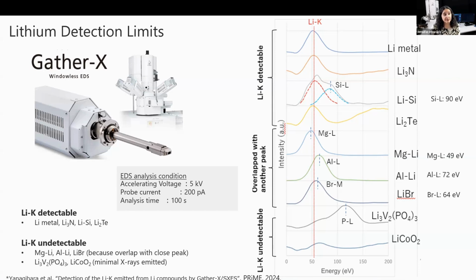Now, there are, of course, detection limits. Lithium is in general not going to produce substantial X-rays if it's within an oxide material, as you can see in the bottom two curves where a lithium peak is undetectable. But even with alloys, if there are elements mixed with the lithium that have even closer overlapping peaks than silicon, and also depending on the percentage of lithium, lithium might be hard to detect with the windowless EDS detector because of the energy resolution of this technique. So here, the center three materials shown, which are alloys with magnesium, aluminum, or bromine, all have very small peak energy separations with lithium. In those materials, the Gather-X would not be the most ideal method for lithium detection.